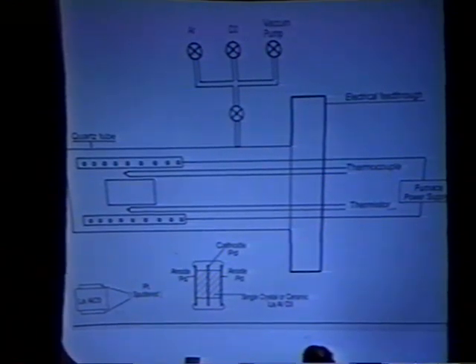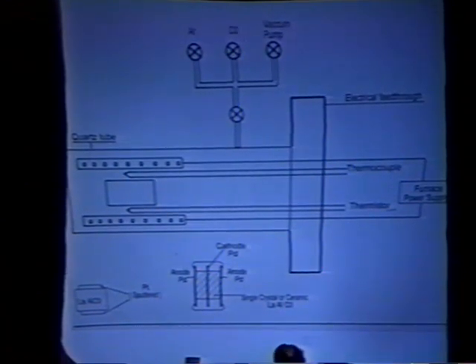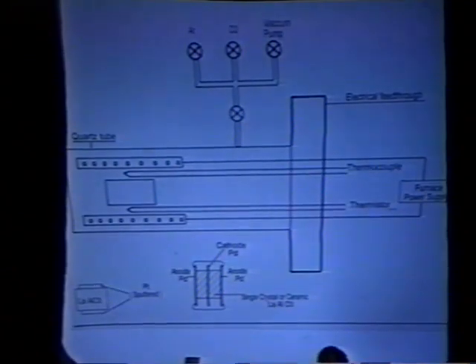So the whole thing is placed inside the tube, and we heat up at high temperature. Now, to tell you a few things about temperature measurements, there's an error here. It's not a thermistor here. We tried putting a PT100 resistor, platinum resistor for measuring temperature, but it melted completely.